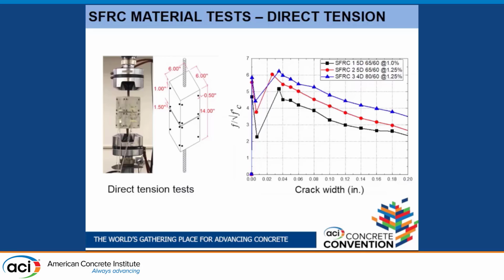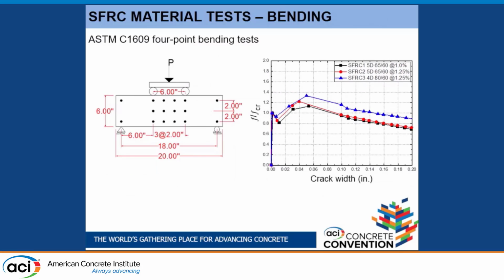What you can see here is 2 out of the 3 mixes, the ones with 1.25% volume fraction, had a peak tensile stress after first cracking that was greater than the first cracking stress. So this is kind of the condition for strain hardening, or a high performance fiber reinforced concrete.